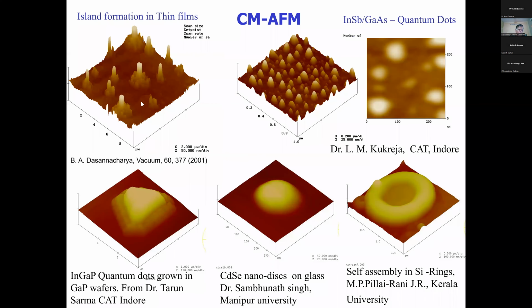And these are beautiful slides for different times, showing how the islands are forming, how the material forms in layer-by-layer growth, island-by-island growth, or island and layer growth. There are a lot of growth modes that can be studied. And these are quantum dots, small particles, even sub-nanometer. These quantum particles can be in a triangular shape, a circular shape, or any other shape. Anything can be done. All of them have very different applications as far as nanophotonics is concerned.